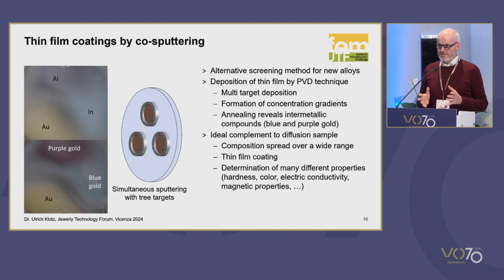quite similar to the diffusion couple. But there's a difference between these two methods. With the sputtering technique, we map the area over a wide range, which makes it easy to characterize the properties. With the diffusion couple, everything is in a very narrow range, so we have to have very specific measurement techniques. So that's a benefit of the thin film coating. On the other hand, the thin films are just thin films, so they might behave different than a bulk material. And so with the diffusion samples, we are much closer to the bulk material. So ideally, we can use a combination of these two different techniques.